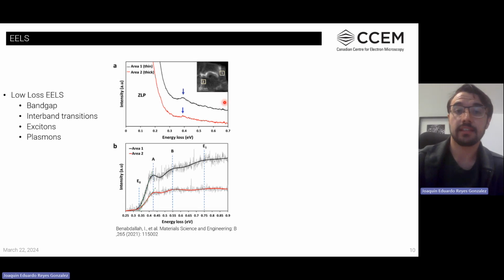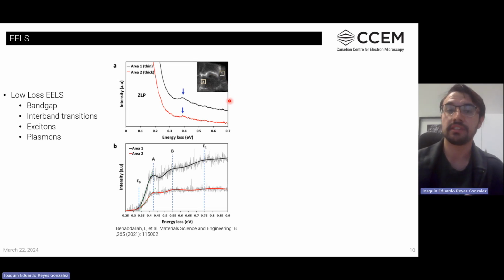In this case, the experiment that we're observing is by using the small probe, locating it in different regions of the black phosphorus, one in this side, one in this side, where the thickness of the material is different, to try to catch what is the behavior, how the behavior changes as a function of the amount of layers.